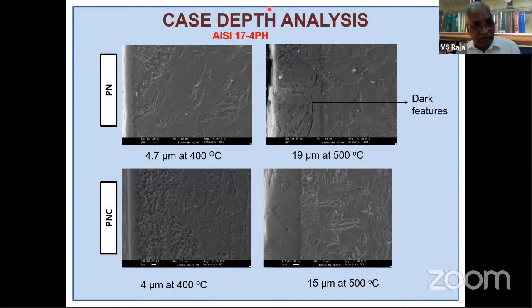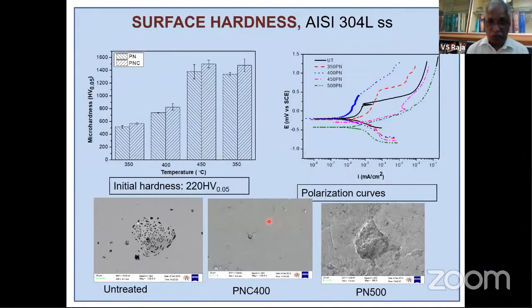You see here the kinds of coatings, you can call them nitriding processes. This is called plasma nitriding, and this is called plasma nitrocarburizing. Okay, so that's what you can do, right? You can get hard surfaces, and these hard surfaces have unique properties of hardness as well as corrosion resistance. I can increase the hardness values, but again, there are various operating conditions, temperatures, concentration of the species that are added to it. A lot of variations are going to be there. Net, it is possible to tailor the surface to have different hardness values and a corresponding change in the corrosion resistance of the section.